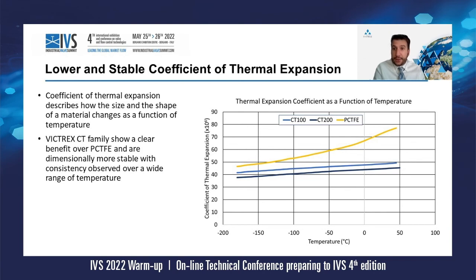In this slide is shown the second biggest advantage of using CT100 or CT200 instead of PCTFE. Both materials have a lower and almost constant coefficient of thermal expansion, not only at very low temperature, but especially as the temperature goes up, where the difference becomes more and more evident.